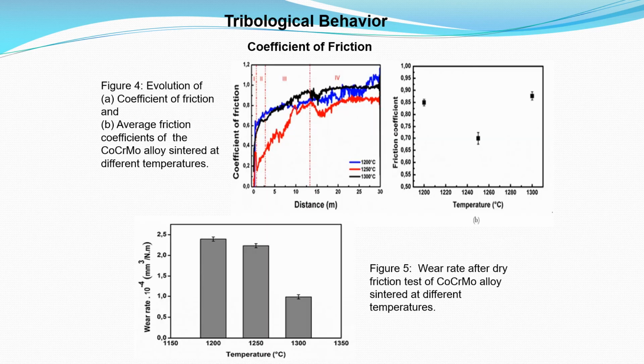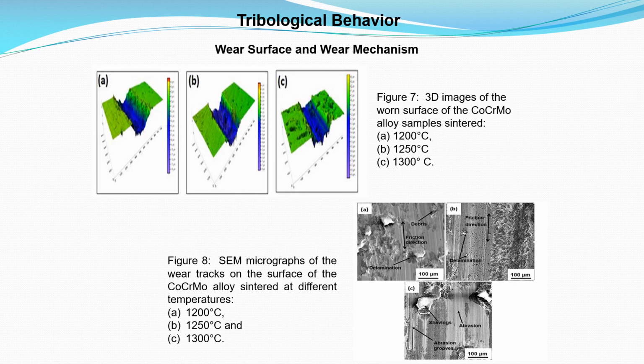For tribological behavior, Figure 4 illustrates the evolution of the coefficient of friction and the average friction coefficients. However, the evolution of the wear rate versus the temperature is plotted in Figure 5. Also, Figure 7 presents 3D images of the worn surface, and the same micrographs of these alloys are given in Figure 8.